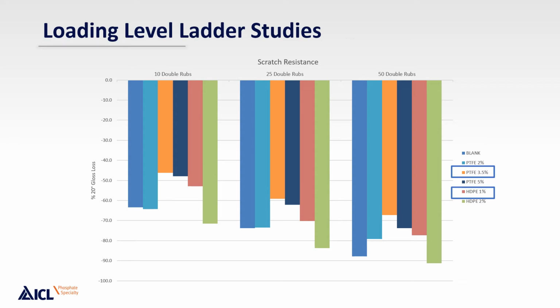So the first of all of the tests that I want to review is, of course, scratch resistance, because that is the most important for the study. This is just a demonstration of the ladder studies that were utilized for each of the additives. So here you can see that for the PTFE, for example, of the 3 points that were run, it was found that the mid-range was the optimal level. In another example, the HDPE that was run, it was the lower level that provided improved scratch more than the higher level. So again, it points to the benefits of running a ladder study with any additive evaluation.